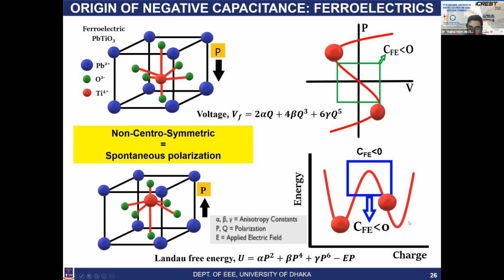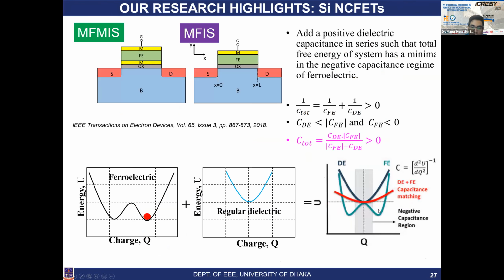Okay, so if you do that, you see that this region over here, which we just saw in the previous curve, this is the negative capacitance region where your capacitance is negative. But this is energetically unstable. If you want to put a charge over here, it won't stay. It will just fall down because that part is unstable. So what you do to make this stable is that you combine the ferroelectric with the oxide capacitance. The oxide has a positive energy landscape. When you combine these two, then at this point you end up with a stable energy where your charge can stay.